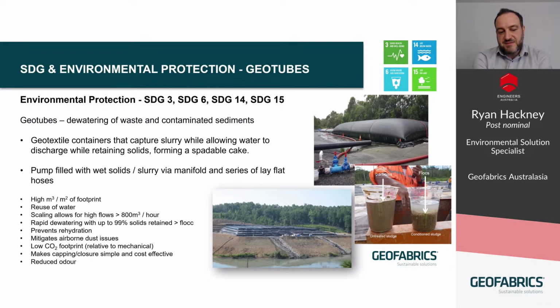So the advantage of geotubes is that we can process high volumes on a smaller square meter footprint. We can use the water that's being discharged out of the tubes, so that can go back into the process, as water, as we know, is a finite resource. Scaling allows for high flows. We can achieve rapid dewatering, as I say, with the addition of flocculants into the process, with up to 99% of the solids being retained.